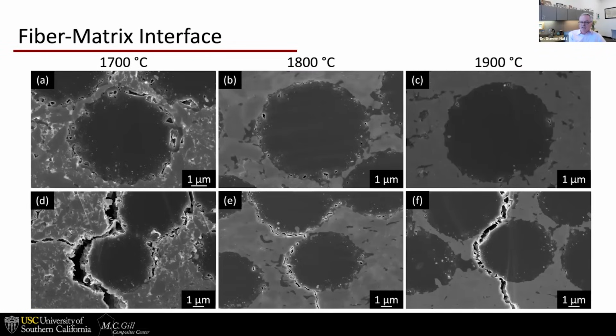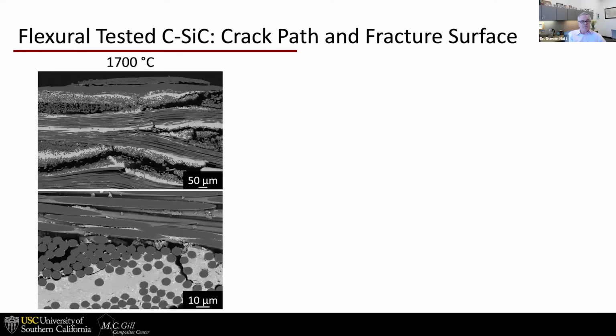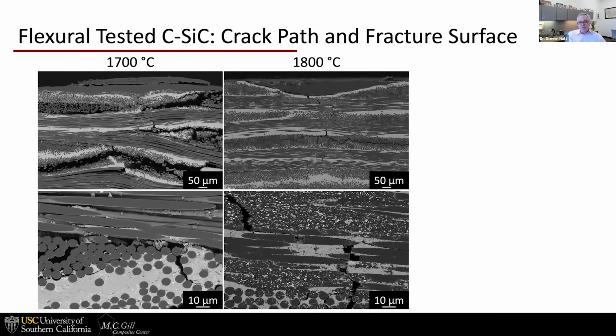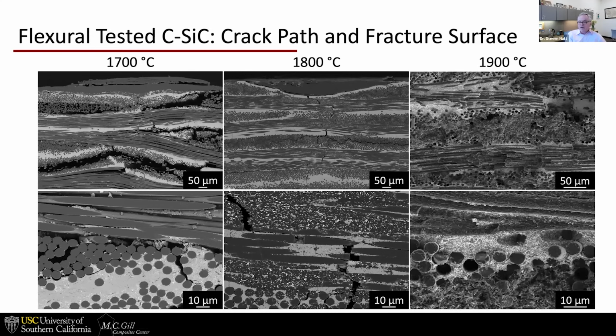But even with reaction, cracks still find their ways around the fiber, which is actually a good thing for ceramic composites. We've also looked at crack paths in this material. Basically, we're seeing interlaminar cracks, transverse cracks. You can see these things propagating through the layers.